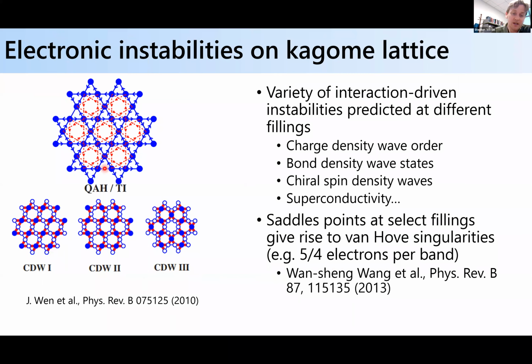And so here I've just, especially if you start to add electron-electron interactions into the system, summarized a few potential charge density wave states or flux phases that can be realized at select fillings. To summarize, there are predictions of charge density wave order, bond density wave states, chiral spin density wave states, superconductivity. And what's germane for this talk is our